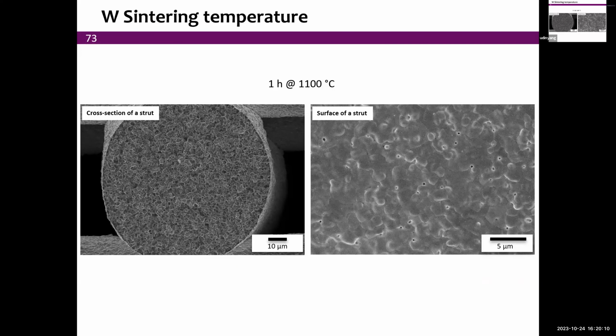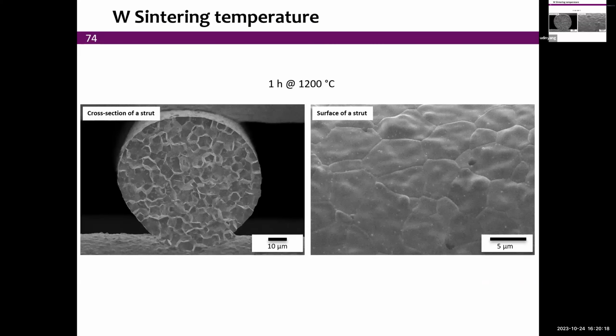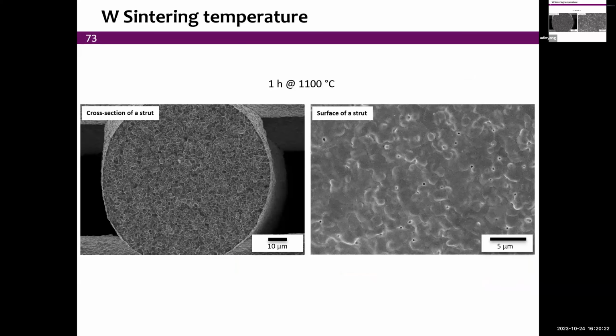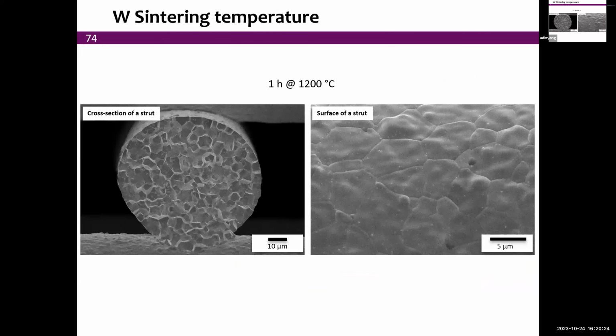And now if you change the sintering temperature, this is again the baseline, 1 hour at 1100 degrees C, fracture surface or cut surfaces, we see very fine grain. And if we go now to 1200 degrees C, let me go back. This is 1100. Again, look at the grain size here. You get, of course, coarser grains as you go to 1200 degrees C, very smooth surfaces.